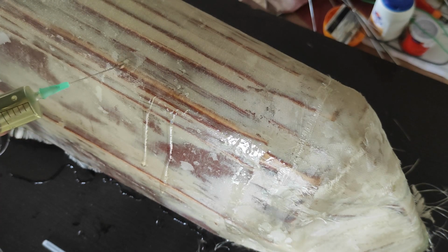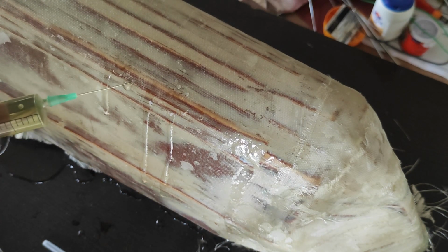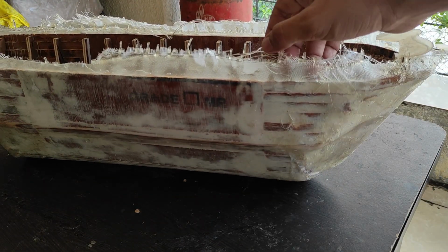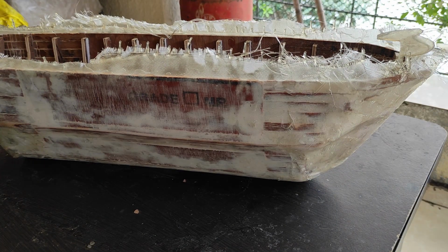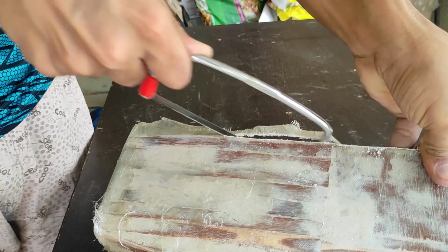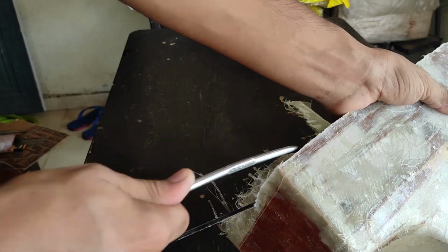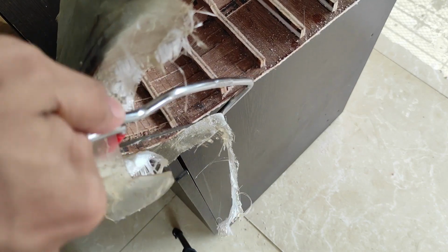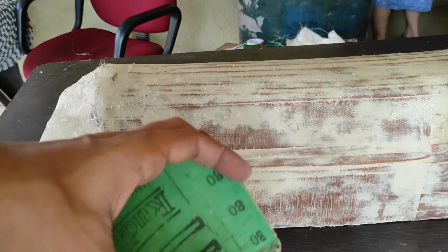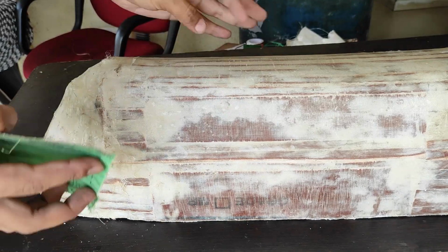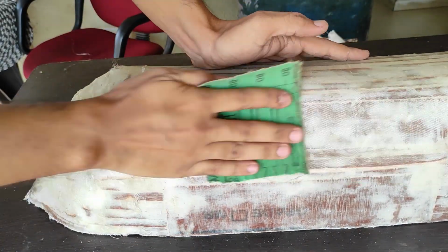I forgot to do it, hence during the curing process, resin by the action of gravity dripped out of the bubble, letting in some air and again formed small air bubbles. After everything was cured, I cut off excess composite and moved on to the sanding process. I used 80 grit sandpaper first and then used some 200 grit to smooth things off.